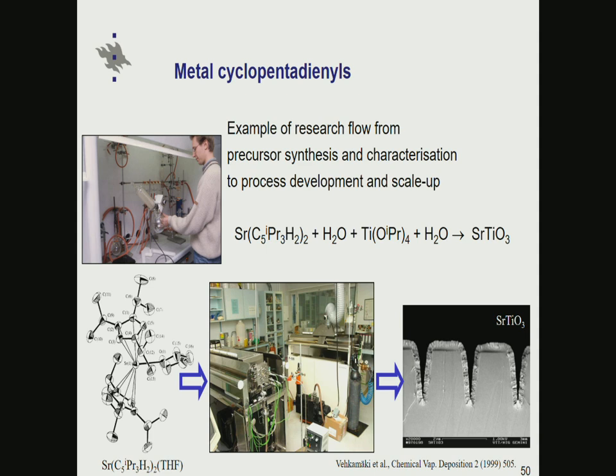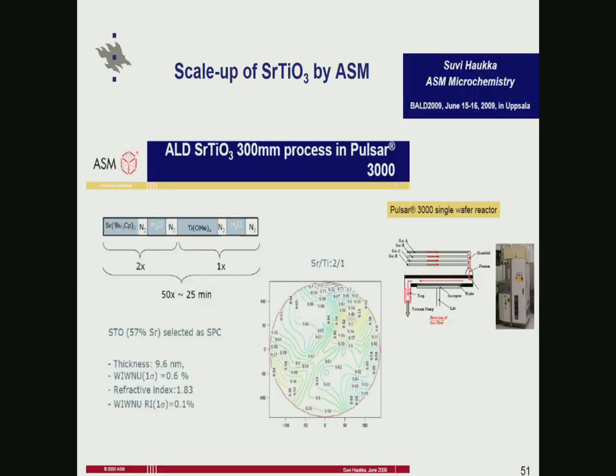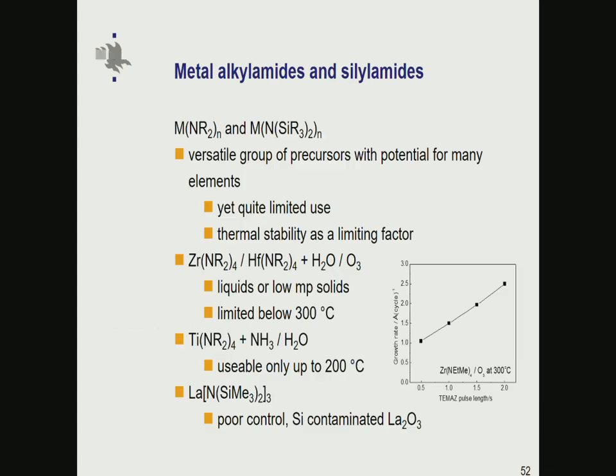Timo Hatanpää synthesized the compound, it was characterized, and verified to be what it was supposed to be. We took that into our growth experiments and proved that we can do nice conformal strontium titanate films with this chemistry. And ASM, our close collaborator, then scaled it up to 300 millimeter processes in their Pulsar reactors with reasonably good uniformity.